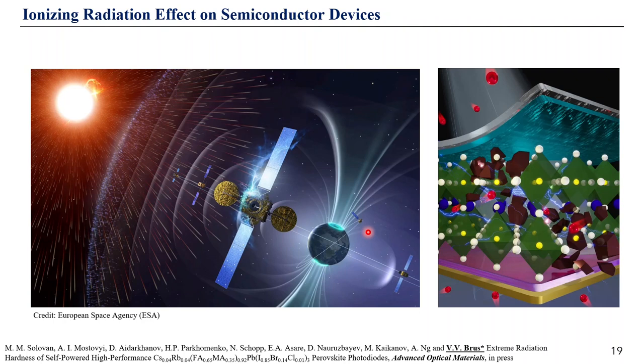And for instance, when protons hit the device structure, they create so-called point defects, vacancies, or interstitials in the material of all functional layers. So these defects result in localized energy levels, and depending on the material, they act either as shallow traps for charge carriers or efficient recombination centers. In any way, that reduces performance of devices, and such conventional optoelectronic material, silicon, unfortunately, is very sensitive to radiation-induced defects and degrades very rapidly. So the substitution of this material with novel radiation-resistant semiconductors and new types of devices is definitely necessary. The bright future of space technology is not the only motivation.